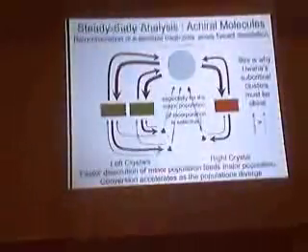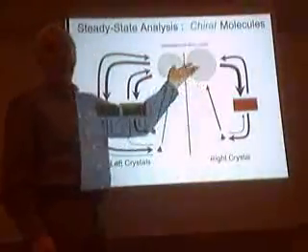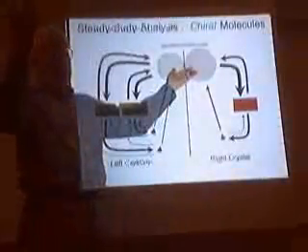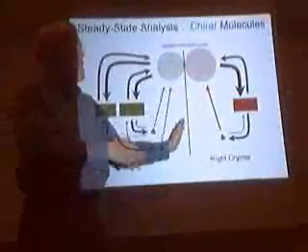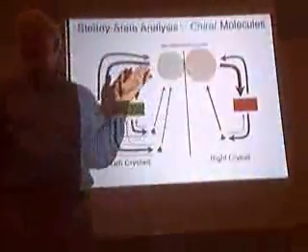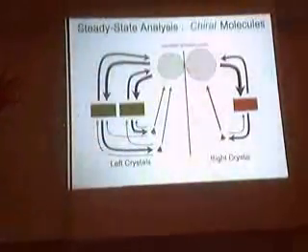Okay. Now, what happens if the pools are separate? Because the molecule in solution is chiral. So this is Vim's case, or your case of the amino acids. Okay, what if there's a barrier here? Then this machine operates, and this machine operates, but they're independent, right? But still, this is faster than this, for exactly the same reason I talked about before. The fact of there being a common pool did not affect that this was faster than this. That was only because of how many incorporation possibilities there are.